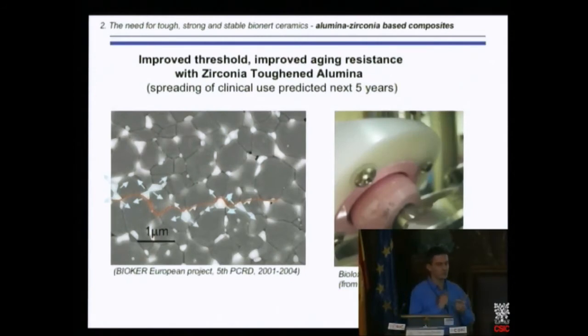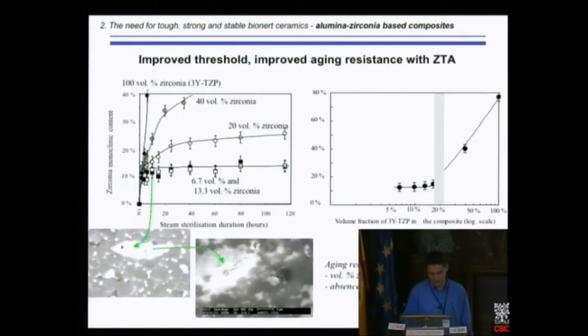So we want tough and strong ceramics, but we also want stable ceramics. So that's why we said maybe we can use zirconia toughened alumina. That's the first strategy, and it's already under clinical use from CeramTec in the form of Biolox Delta ceramics. So this is a Biolox Delta ceramic mounted on a hip simulator. The pink color is due to an addition of chromium, but it's quite a standard, classical alumina zirconia composite. And we said we should have a higher crack resistance of these composites. But what about stability? We have to know about stability.